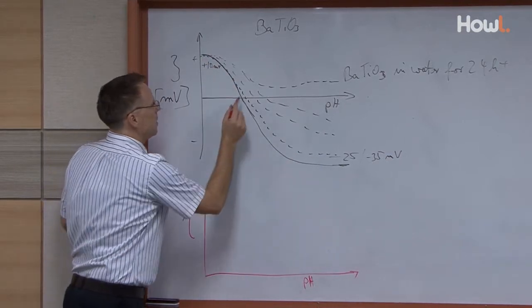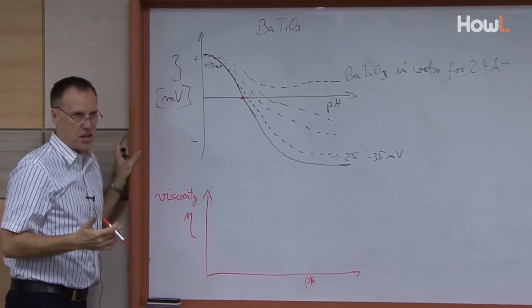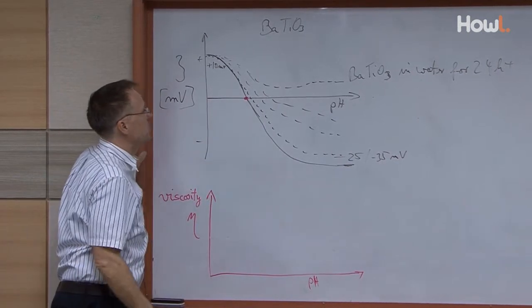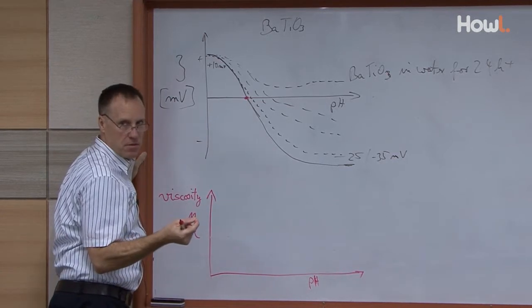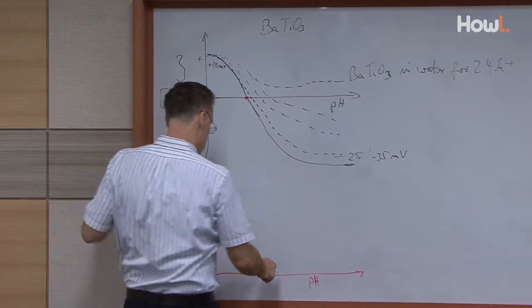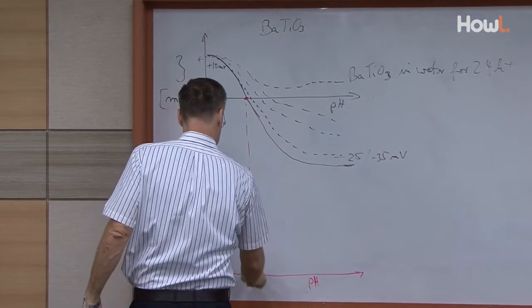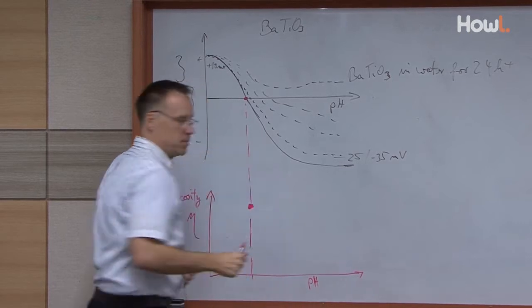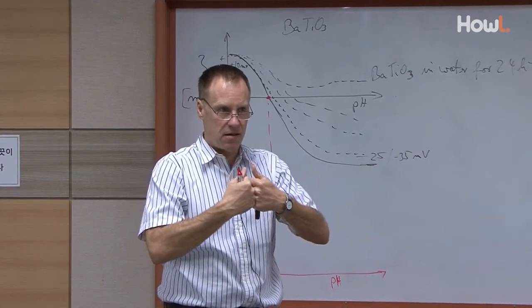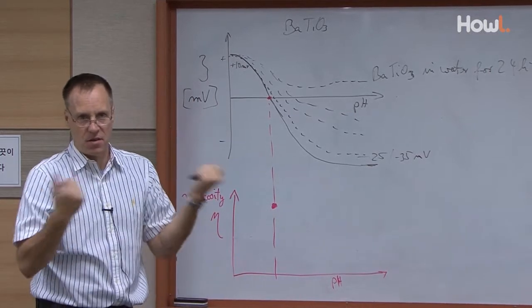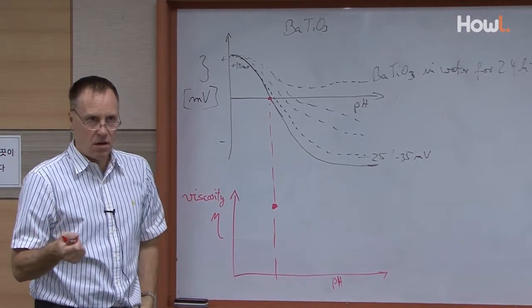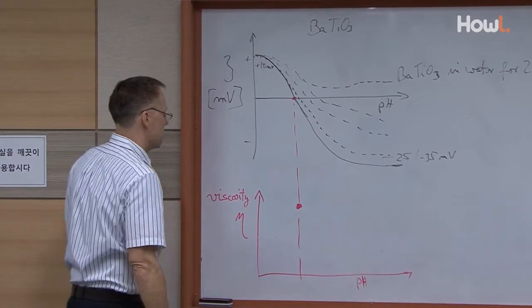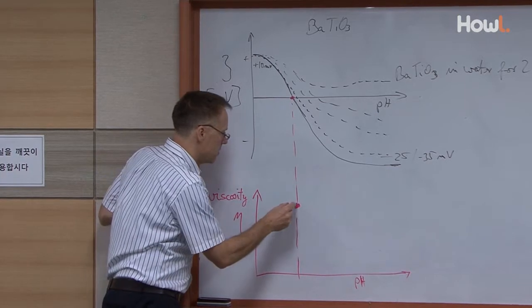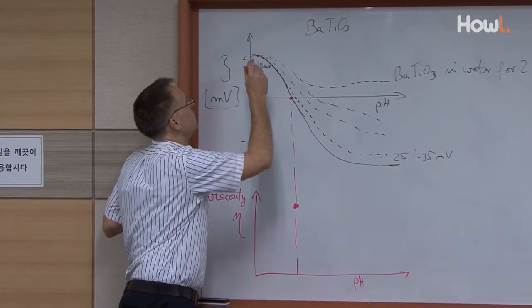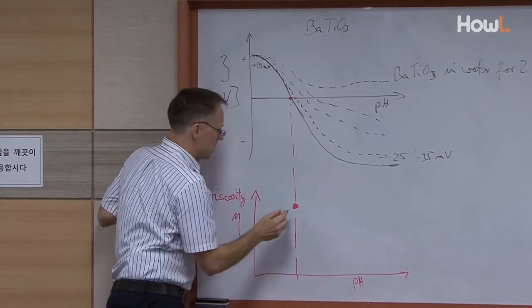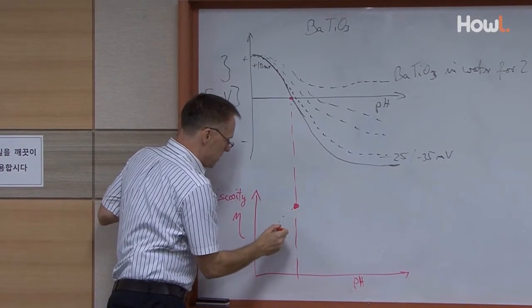So what happens if you're at this point here, when you use this spreadsheet for calculation, or just summing up what you have here: you have van der Waals attraction and no double layer repulsion. That means at this pH, directly down here, you will have the highest viscosity, meaning the highest resistance to flow, because particles stick together, and it can even be so high that it's a solid, so that you can't measure viscosity anymore, and it gives you an elastic response instead of a viscosity. Yeah? So now, if we go to here, 10 millivolts we said is not really dispersing, but it's a little bit better,